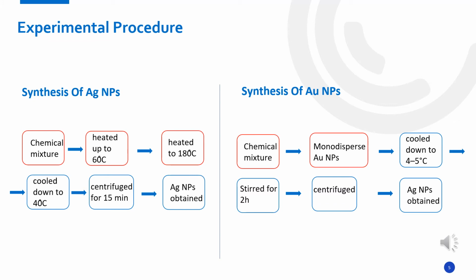For Au nanoparticles, we will have a chemical mixture that will give us monodisperse Au nanoparticles. In the next stage, the temperature of the solution is adjusted to 4 to 5 Celsius with the aid of an ice bath and stirred for 2 hours. Then the solution is centrifuged after the addition of acetone and ethanol, then Au nanoparticles are obtained.